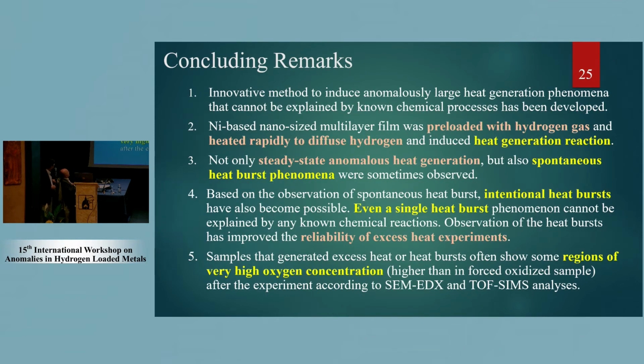Okay, I would like to conclude my presentation. An innovative method to induce anomalously large heat generation phenomena that cannot be explained by any known chemical process has been developed. A nickel-based, nano-sized multi-layer thin film was preloaded with hydrogen gas and heated rapidly, and the diffused hydrogen induced heat generation reactions. Not only steady-state anomalous heat generation, but also spontaneous heat burst phenomena were sometimes observed. Based on the observation of some spontaneous heat bursts, intentional heat bursts have also become possible.